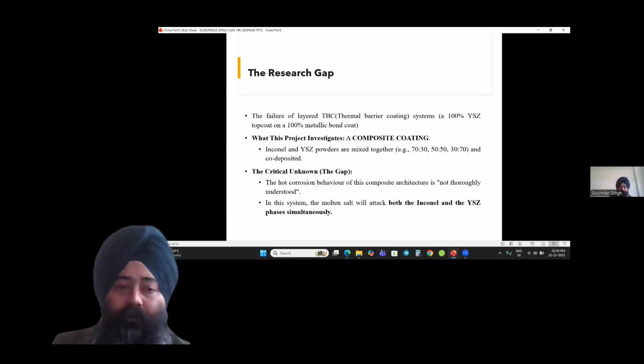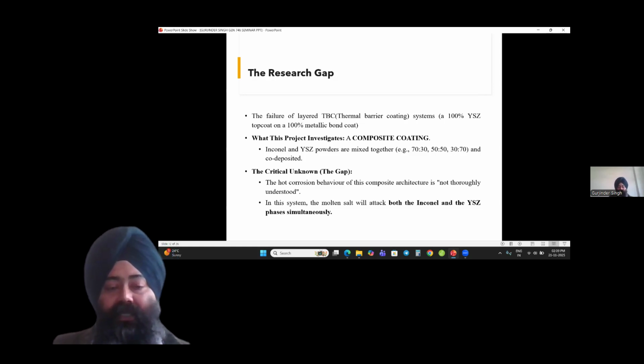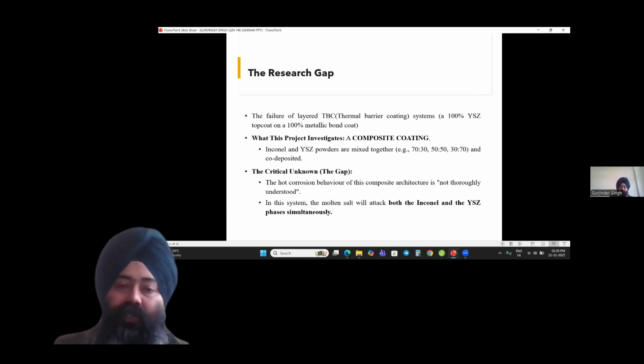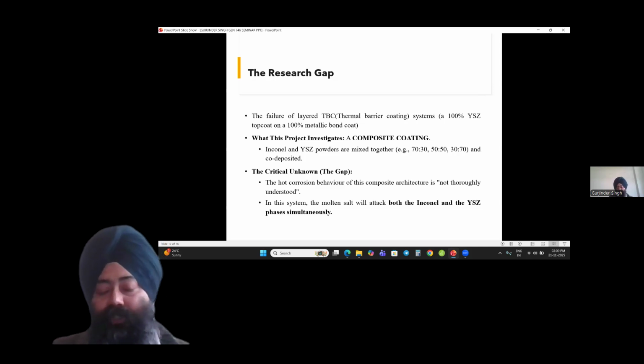And we are planning to investigate our project in the composition of YSZ and Inconel. First, we are going to mix the Inconel and YSZ in the ratio of 70:30, that is 70 is Inconel and 30 is YSZ. Then 50:50, then 30:70.